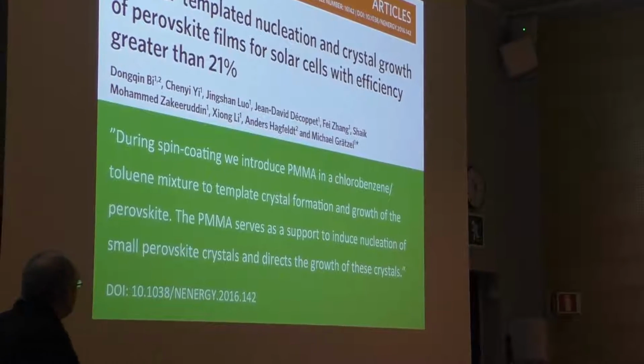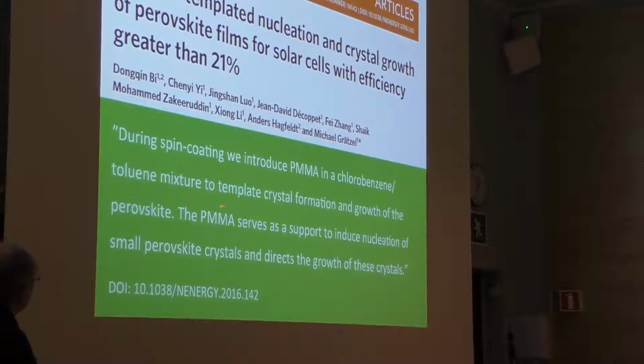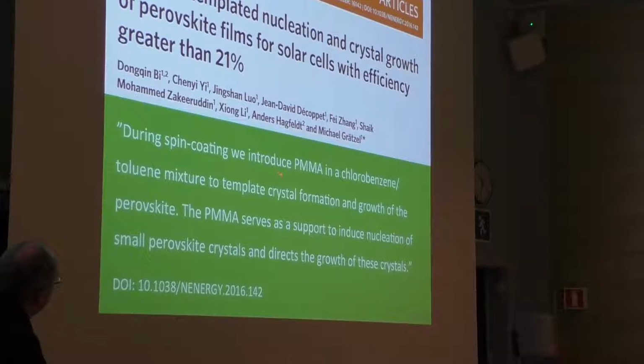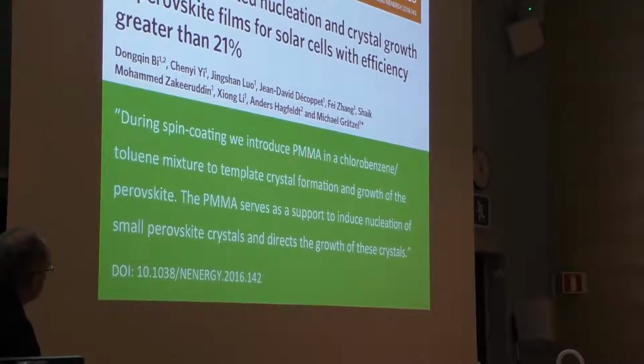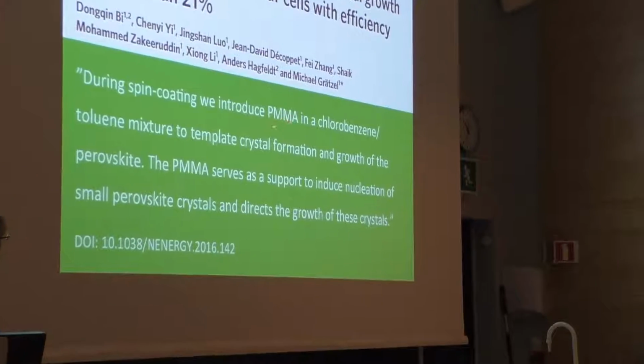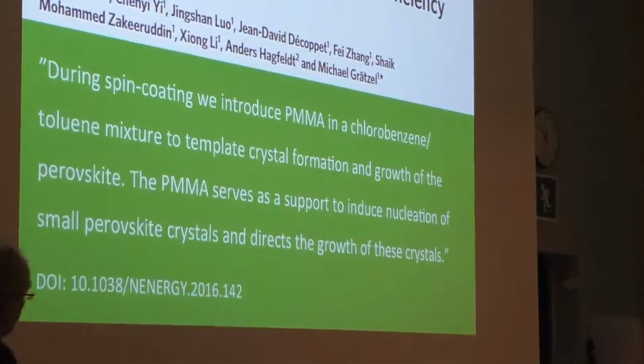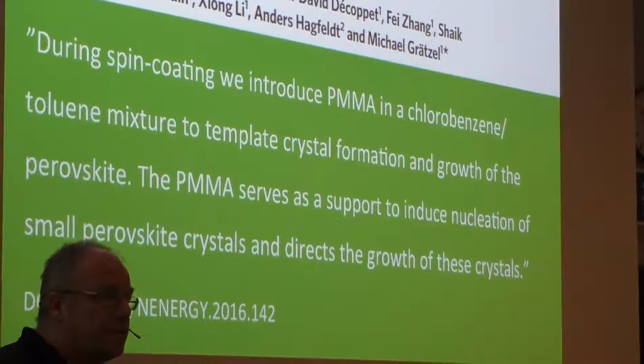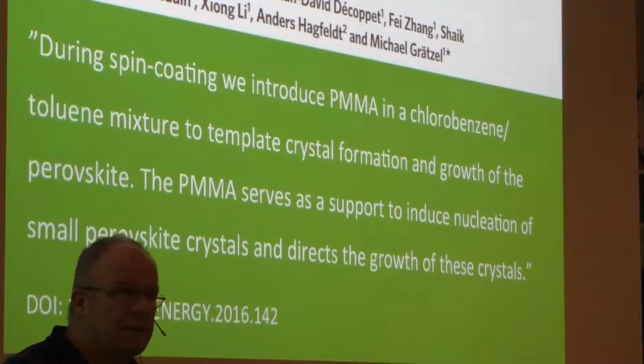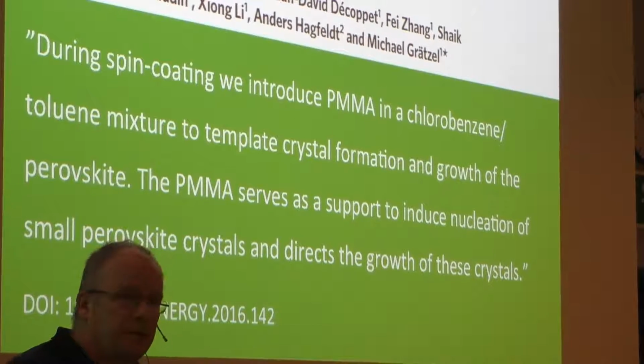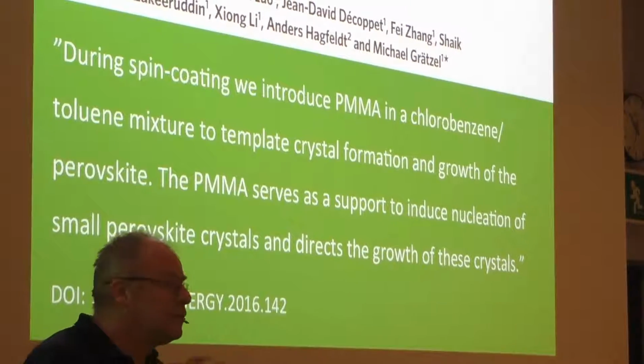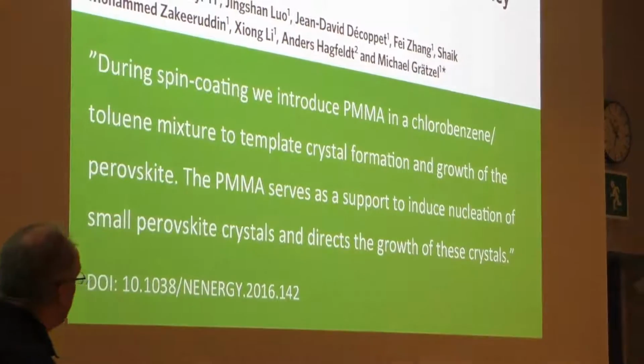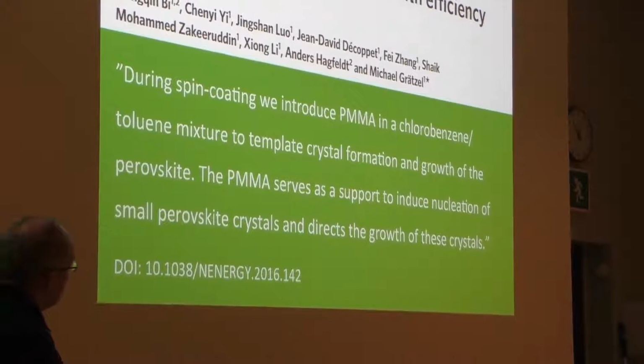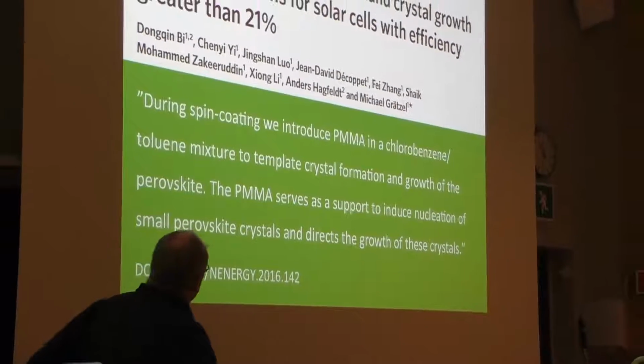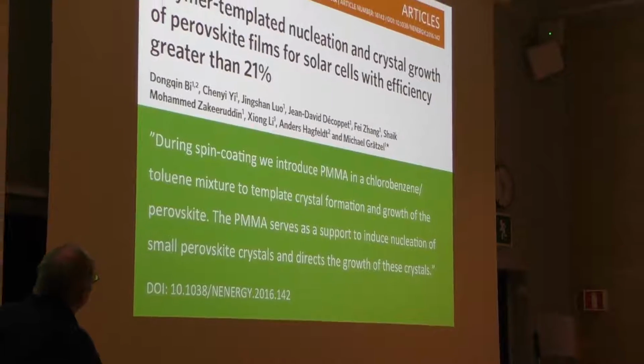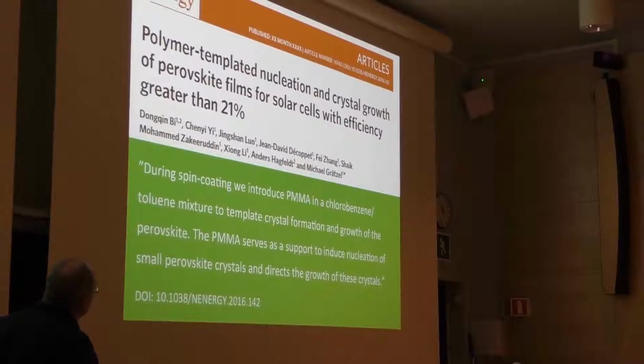We continued the optimization, and this is a recent work where Dongqin, a postdoc, worked on additives in the formation of the perovskite with PMMA. It forms a complex with lead iodide. It slows down the crystallization. We form larger crystals. So a big game for perovskite is to form larger crystals and to reduce grain boundaries, let's say. And if you do that, you get higher voltage and less recombination. So this was certified at 21.0% efficiency.